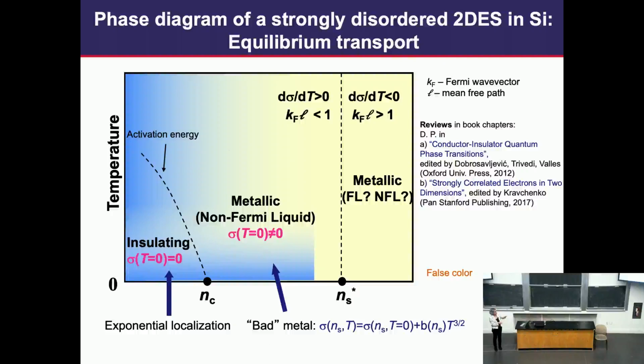Basically, what we found from the temperature dependence is that at low densities, in the zero temperature limit, conductivity is zero, which is the definition of an insulator. Above some critical density, the conductivity in the zero temperature limit is finite, which is the definition of a metal.